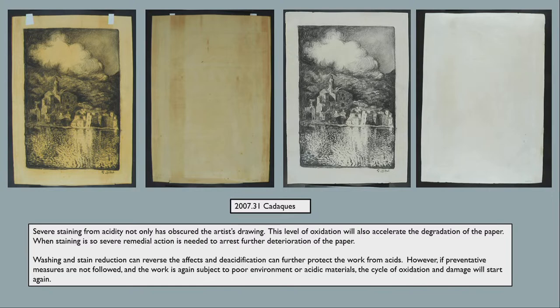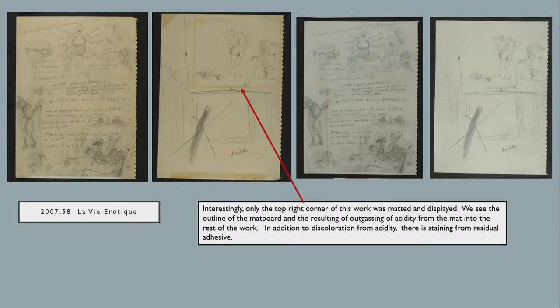However, if preventative measures are not followed and the work is again subject to poor environment or acidic materials, the cycle of oxidation damage will continue. So there it is afterwards. And you can still see a little bit of staining in the back of the piece, but it's a lot better. And this is where you stop at a certain point to know that doing anything more may have caused risk to the paper fibers, because it is possible to weaken paper through too much treatment.